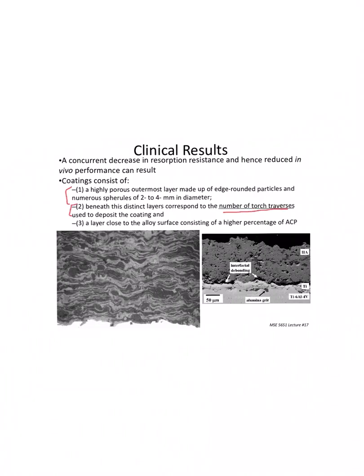Again, the number of torch traverses is visible in the microstructure, as is shown here. This is an alloy coating. You can see the tree ring history of that coating and how it was deposited. You can probably count the number of passes by looking at that surface.